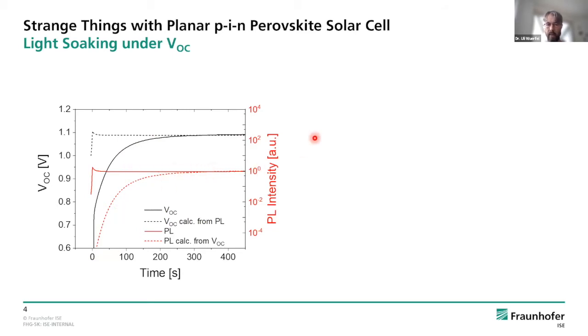And the dashed lines tell you what you would expect if you apply the usual theory. So if we take the black line as, let's say, the given result, then we can calculate what kind of photoluminescence intensity we would expect if everything would be normal. And this is the dashed red line. And you can see it's very different from the one which we actually measured. You can do the same also the other way around. You take the PL signal as the input result and calculate from that the open circuit voltage which you would expect. And this is shown here in the black dashed line. So we can see something is not normal here.